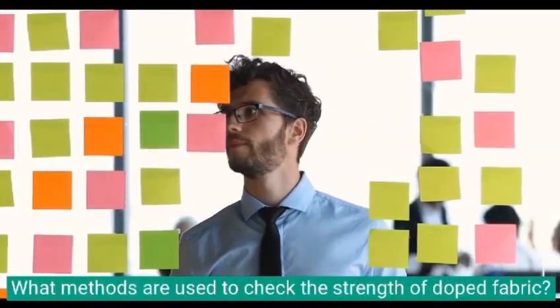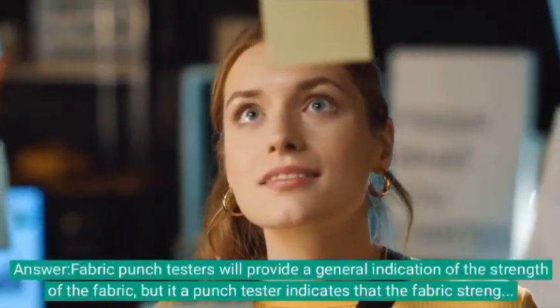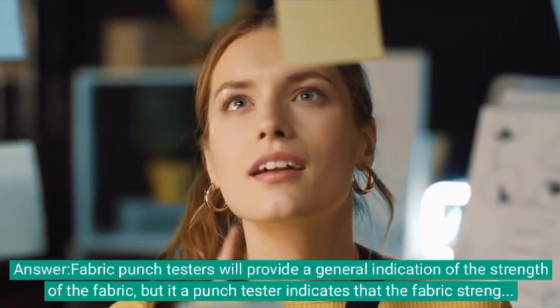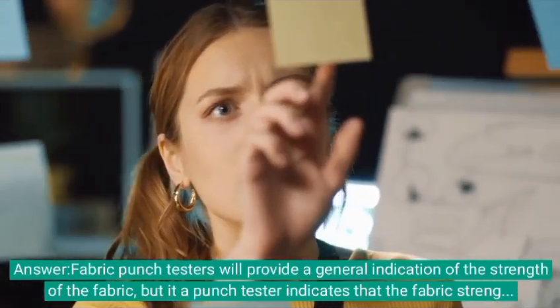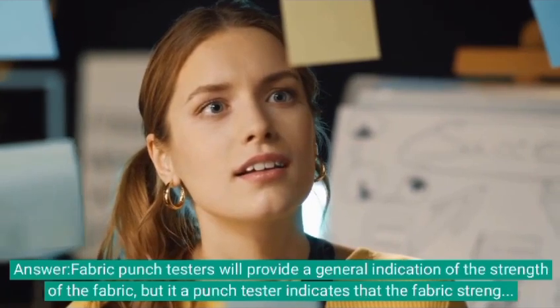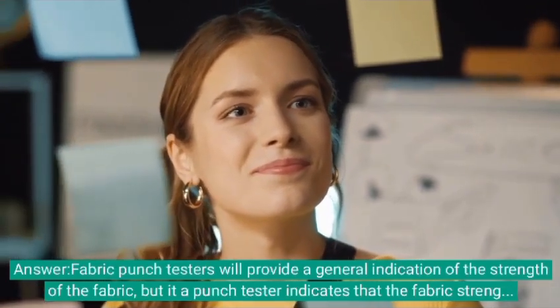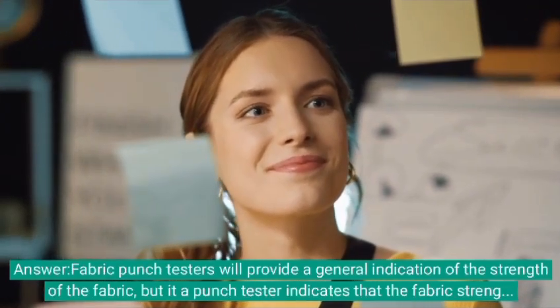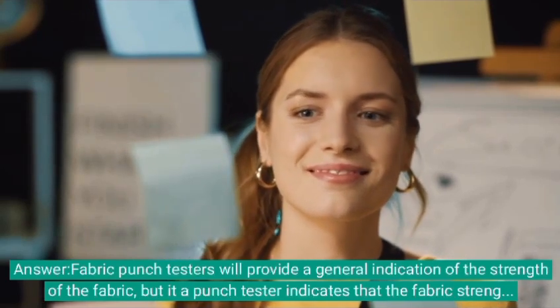What methods are used to check the strength of doped fabric? Answer. Fabric punch testers will provide a general indication of the strength of the fabric, but a punch tester only indicates that the fabric strength is marginal. A laboratory test should be performed to determine the actual strength of the fabric.